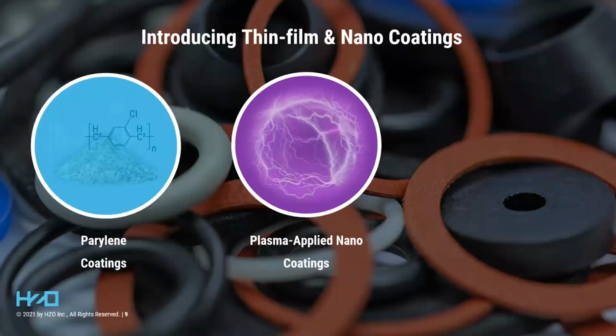Conformality ranges from line of sight to not quite as conformal as Parylene, and film density and protection levels can vary greatly, but surfaces can be functionalized easily. You have a lot more levers you can pull when it comes to a plasma applied nano coating, between chemistry, energy, pre-treatments, things like that. So you can get a pretty wide variety of chemistries on your substrate.